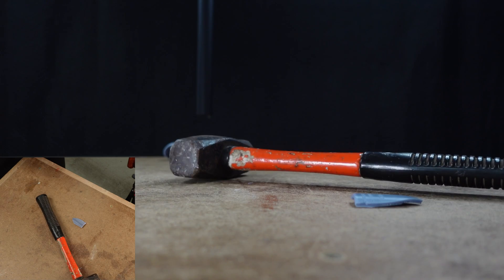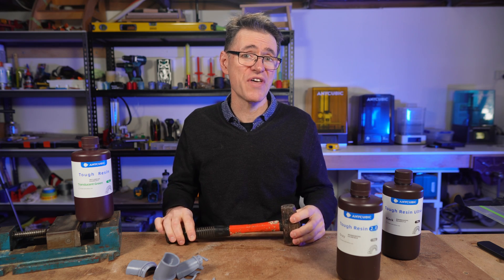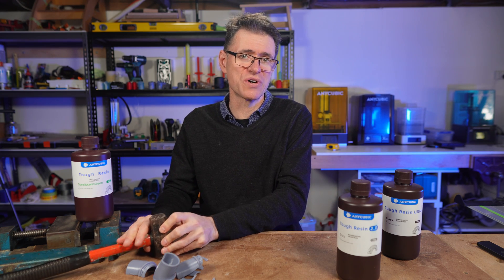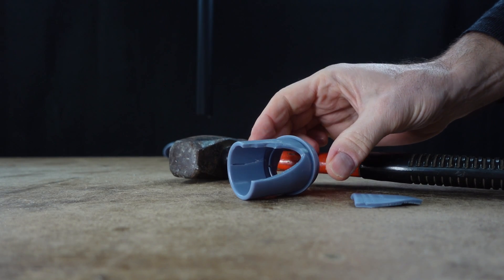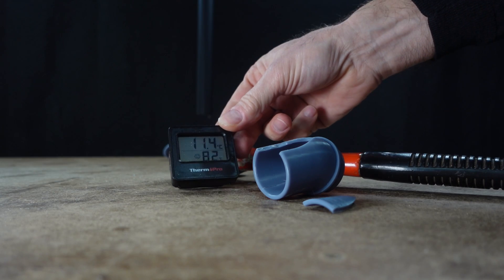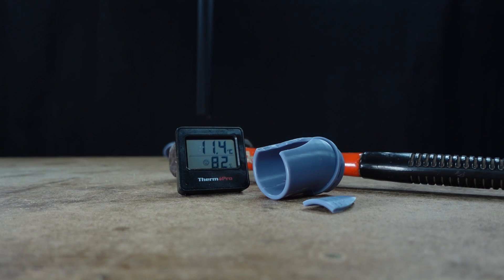I'm just dropping this hammer onto the part with its own weight like this. The hammer weighs one and a half kilos and the handle is 300mm long. It's my not too scientific hammer drop test. So far it's not looking that tough, but the test is taking place in cold conditions — it's only about 11 degrees in my workshop, and that could be making the resin more brittle.